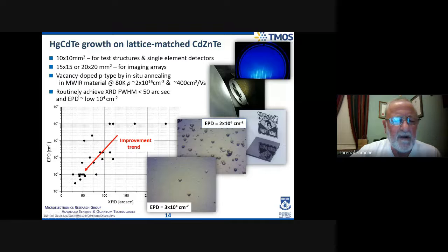The typical numbers that you need to get to, this is etch pit density. You need to get etch pit densities down in the low 10 to the 4 per centimeter squared. You need to be down in this quadrant before you can really fabricate infrared imaging arrays. If you're down in the low 10 to the 4 per centimeter squared, then there's a likelihood that you will fabricate arrays with a detector yield above 99%, which is what you really want for an imaging array. If you're up at higher numbers, your pixel yield in your imaging array is going to degrade very rapidly.